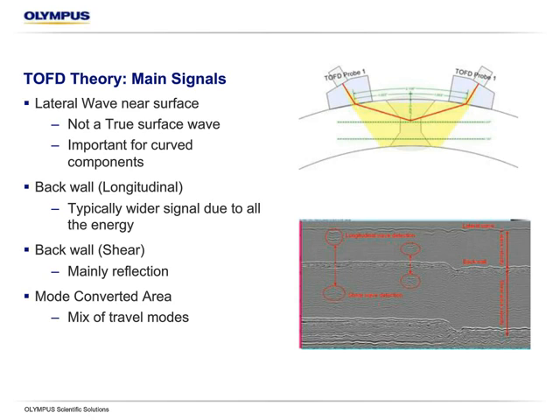This is typically a very wide signal because the back wall of a pipe or the back wall of a plate gives a lot of surface area for both reflected and diffracted energy to occur. So we're getting a lot of energy coming off that, and it's very consistent. It's a very big target. And then we have typically another big reflection from the shear wave that we showed coming out at about half incidence. Mainly reflection. We can see it in the bottom picture as well. It's the third main line across.